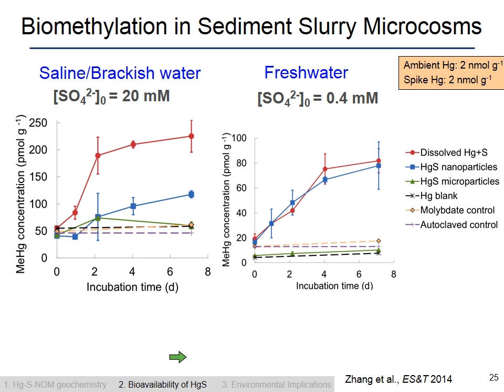So this is a freshwater sediment taken from closer to the delta part of the San Francisco Bay Area, where the sulfate concentrations are much lower. And what we see is an equal amount of methylmercury produced in those microcosms that get dissolved or nanoparticulate mercury. And there's no difference between the dissolved and the nano. You also notice that the absolute amounts of methylmercury produced here on the right are less than the amounts produced on the left.